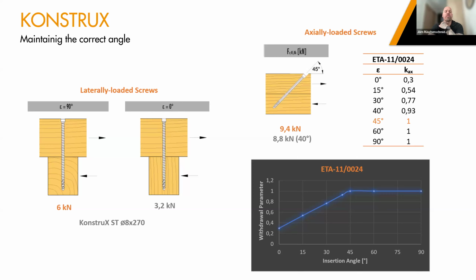So I think it's quite important to know how the change of angle is affecting the screw and how we make sure that your design, especially working with inclined screws, will be maintained on site. If you look on the left graph, seeing laterally loaded screws, we have a perfect efficiency if we are at 90° on the lower part, so perfectly perpendicular to grain. And if we are completely with the grain, we lose a lot of the capacity. You see, getting down at an 8x270, for example, from 6 kilonewton to just 3.2.